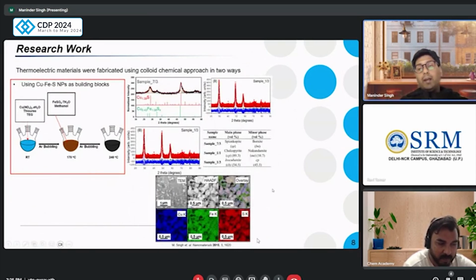Then, to identify and characterize whether our nanoparticles are the same as what we want to create, we did XRD. XRD is X-ray diffraction, where each nanoparticle that you have created has characteristic peaks, the Bragg diffractions you can see here, and with all the XRD patterns we can confirm that we have the desired end product that we wanted to create. And these are the TEM and certain high-end instrumentation where you can identify if there is sulfur, if there is iron, if there is copper. And the overlay of all these images can tell you that copper and sulfur, iron and sulfur are there in a particular ratio.